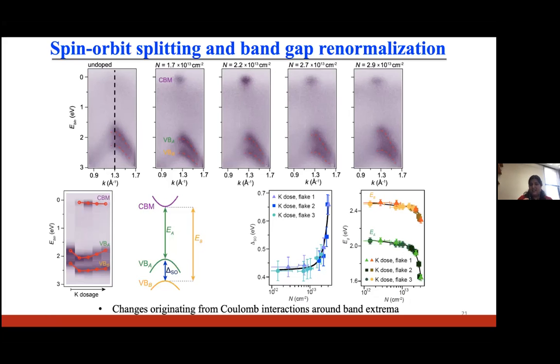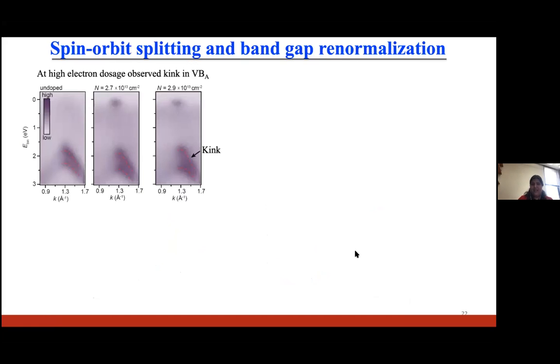We can understand this more if we look at what is happening at the high dosages. If you pay really good attention, you will see that in the upper branch here, we have a kink. It turns out if we can understand the origin of this kink, then we can understand why we are seeing an enhancement in the spin orbit splitting. So I'm going to give you a hand wave, a simple picture of what we understand is happening here.